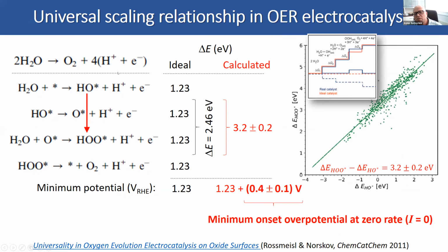Some of the steps are easier than the others, which means that the other steps are more difficult. Hundreds of calculations for different electrocatalytic materials made by density functional theory, when you put them on a graph, show that the difference in the adsorption energy between the third and first adsorbate gives you on average 3.2 electron volt instead of 2.4 electron volt. So this is the reason why you have the overpotential.